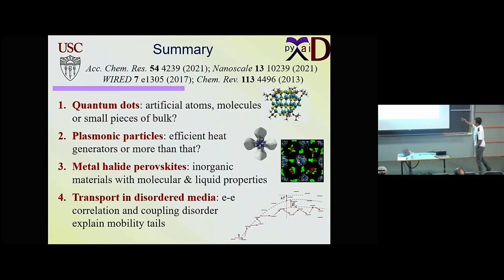So we model excited state dynamics in various types of quantum dots. We look at interfaces of quantum dots with quantum dots or with other materials, which give us some idea of the transport between them, charge transfer, energy transfer. So chemistry is important. Also, in nanoscale materials, you have this Auger process, charge-charge scattering, which also plays important roles in transport. Plasmonic particles have states that delocalize very far, and that is important not just to create plasmon resonance that absorbs light, but also to facilitate transport. You have 1 nanometer gaps, and you can still have efficient transport across those gaps. And perovskites are very interesting materials. They combine properties of inorganic matter and organic matter and liquids, rich physics, and you can have finer effects in disordered media for transport. Anyways, thank you so much.